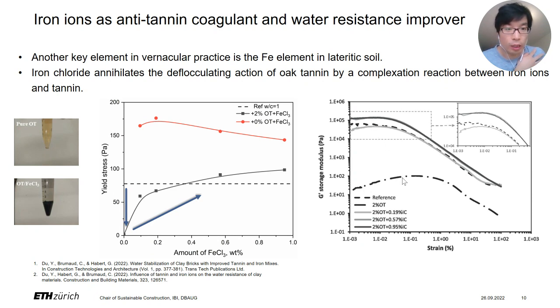After putting in oak tannin, the paste is more liquid, so we have a lower elastic modulus and higher critical strain. But once we put in iron chloride one, the elastic modulus suddenly increases to a value close to our reference and even higher. And the critical strain suddenly gets shorter, even lower than our reference. That means the deflocculation action brought by the tannin has already been removed. The paste is not liquid anymore, and is now in the coagulated state.